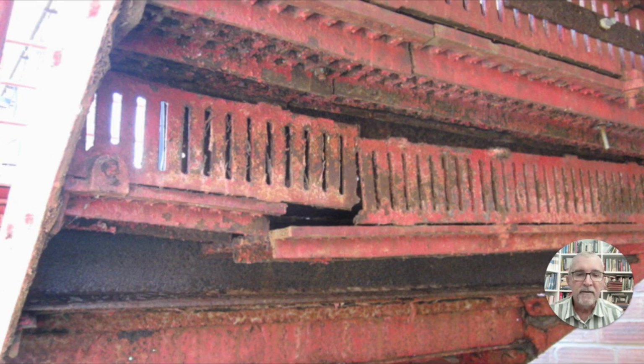So here we see a staircase, a fire escape staircase it is actually, coming out of the back of a building and created with sectional metal parts which have fractured due to corrosion of the metals. And it's this corrosion, this rusting and gradual deterioration of the metalwork which ultimately leads to its failure. And it's a very common occurrence, actually. Even if you've not had much experience of it, it's always the same when you get ungalvanized metals in the presence of moisture, which can often just be poor painting, or exposure to saline environments such as near the seaside, and then that rusting leads to ultimate failure.